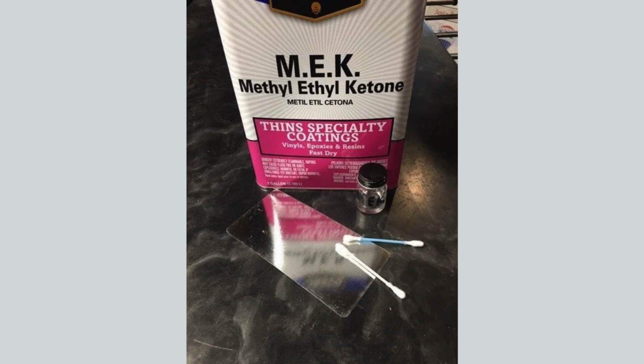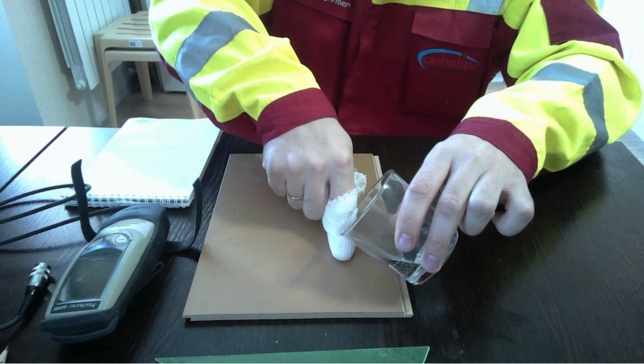4. Examine the coating film for the effects of the testing. If the coating film has been removed down to the substrate, reconduct the test in a new area of the coated sample using a lower number of double rubs. If the coating film has not been removed down to the substrate, reconduct the test in a new area of the coated sample using a higher number of double rubs. 5. Repeat the testing process until the number of double rubs just removes the coating film down to the substrate surface. This is considered the MEK resistance of the coated sample.